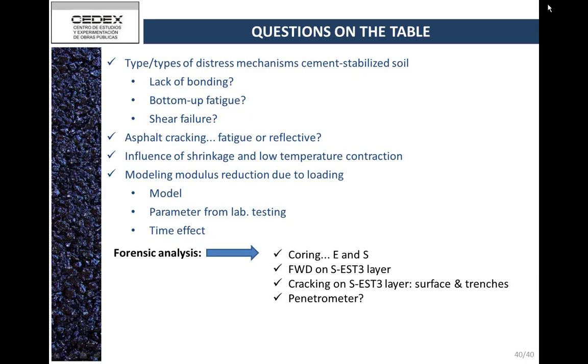When you have the quality of the bond changing, and the amount of bond as it's going down in the inner layer, I think as a condition of the quality of the tack and the material used in the tack, you can see a back-calculated debonding effect when you don't have full mobilization of material. It's almost like just a lack of bond that affects your back calculation process, but there's not a full mobilization going on.